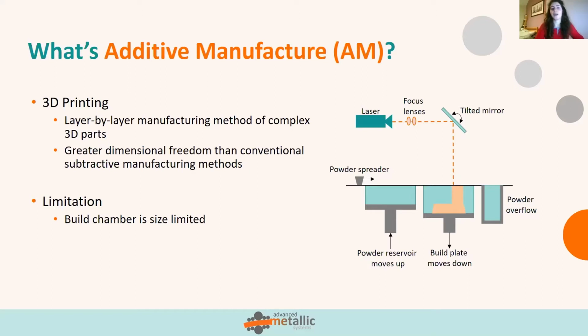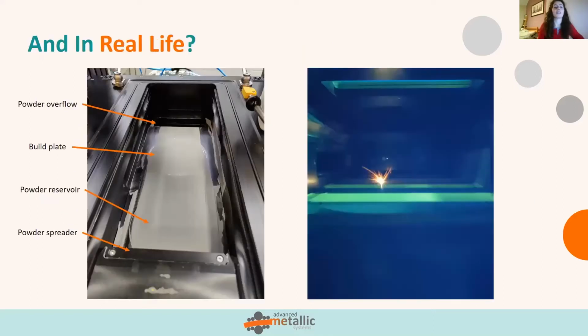I realize this is quite an abstract concept, so I've included this to show you what it's like in real life. You've got the powder spreader at the very front of the image on the left, and the powder reservoir, then the build plate, which has the first layer of powder already on it, and then the overflow of the powder at the back. Any powder that isn't melted by the laser can be reclaimed, sieved, and reused in the future.